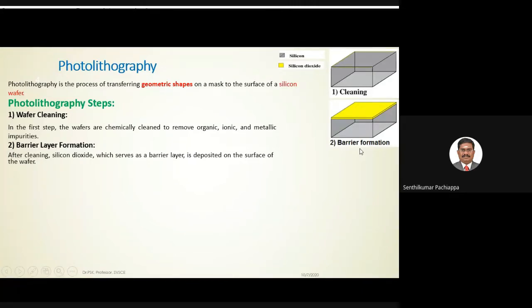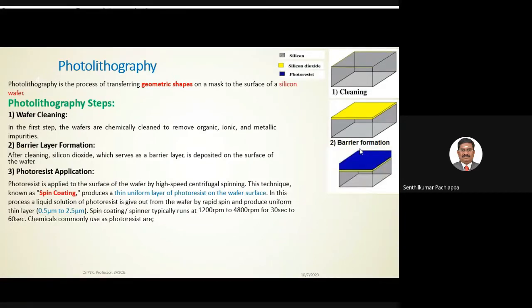In the photoresist application, the photoresist is applied to the surface of the wafer by high-speed centrifugal spinning. It is a thin film technology, a spin coating, to produce a thin uniform layer of photoresist on the wafer surface. The liquid photoresist solution is spread out over the wafer by rapid spin and produces a uniform thin layer. The thin layer thickness is 0.5 micrometer to 2.5 micrometer.